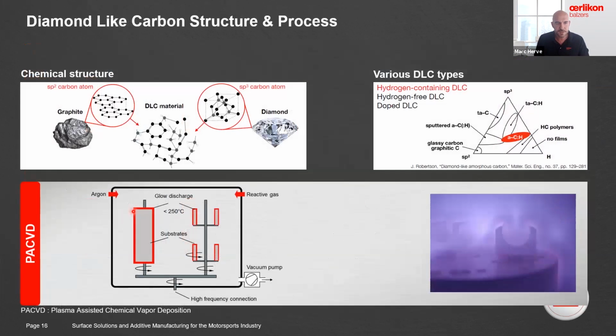So we've got to be careful about the material of the parts. Another coating technology which is very well used is what we call the DLC. DLC stands for diamond-like carbon. So it's basically an amorphous structure between graphite and diamond. This is why the DLC is very interesting, because it gives a very low friction that you get from the graphite, but then the very high hardness from the diamond.